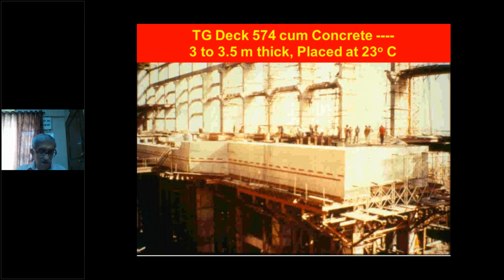placed at 23 degrees centigrade. So we had made such a mix, so that the temperature goes down to 23 degrees. Because we were doing this concrete, we had anticipated about say 38 degrees centigrade to 40 degrees.